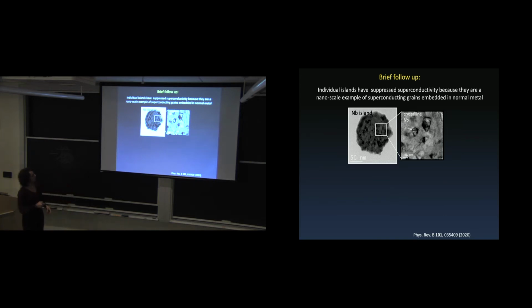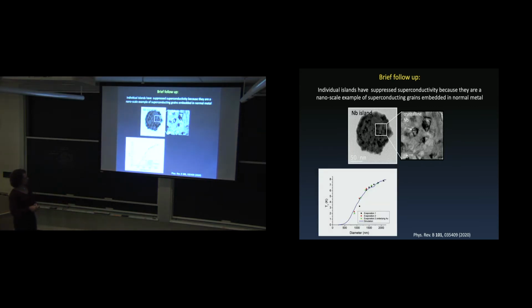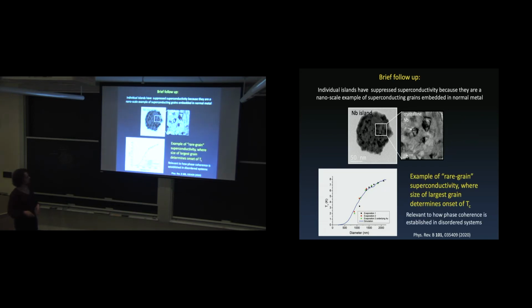And we studied this more and found that the islands themselves are actually granular with crystals of niobium in them. And we discovered that this was another example of a sort of granular superconducting system where the TC basically depended only on the size of these grains in the island. And so this is an example of what we call rare grain superconductivity, where just the size of the largest grain determined the onset of TC. And this is interesting because it's related to a lot of other disordered or phase-separated systems where the onset of correlations is determined by the size of the largest region, or the largest grain in this case. And so that's what was causing suppression of superconductivity in our islands, and also what then coupled them together.